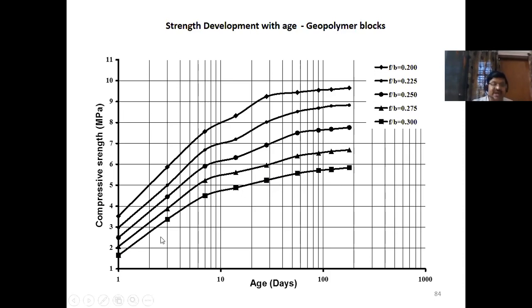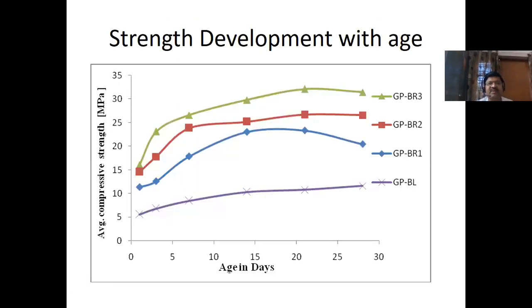And also we can say that at the age of 1 day, it is possible to get 3.5 MPa. As per the code, if you want a brick of 3.5 MPa, that's enough. Normally we wait 3 to 4 months for fire clay bricks. In case of concrete, we may have to wait for 10 or 15 days. But in case of geopolymer, we get the strength of 3.5 MPa on the first day itself. So it is very fast in curing. This is the advantage of geopolymer blocks.